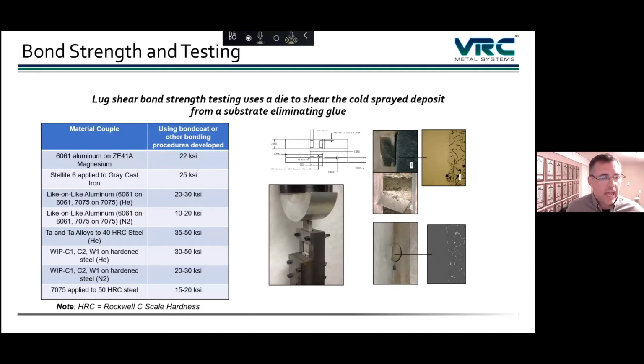Now, we're not quite that close on all the other materials here. You see some steels that are 40 Rockwell C with tantalum on them, for instance, that can be in the 35 to 50 KSI range, still significantly higher than a thermal spray coating would be, for instance, where you can actually use this as a structural member, but not quite as high as the base steel strength itself. So you do have to plan the design of interfaces sometimes if you're taking major structural loads through the deposit, but it can be done, and it has been done.